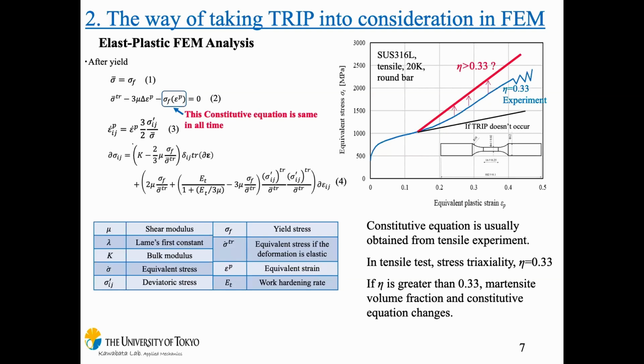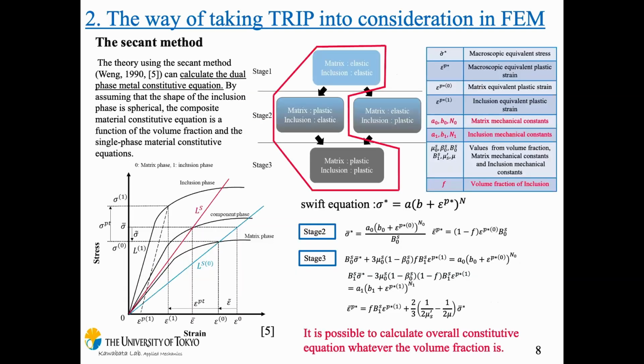because the constitutive equation can change depending on the amount of TRIP. So, for example, if the stress triaxiality is higher than that in the uniaxial tensile test, the amount of TRIP is also increased, and as a result, the yield stress is also increased. And this is the problem. So I try to solve this problem. So I use the secant method.